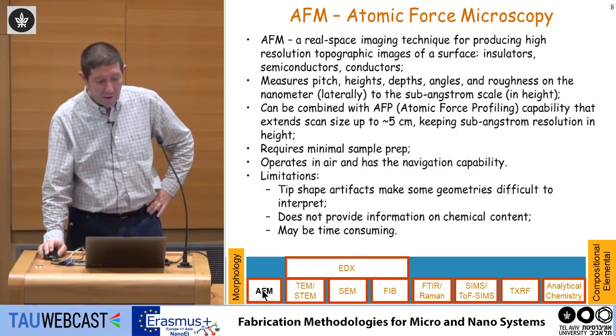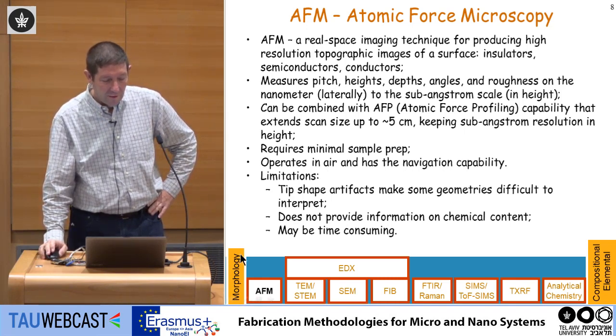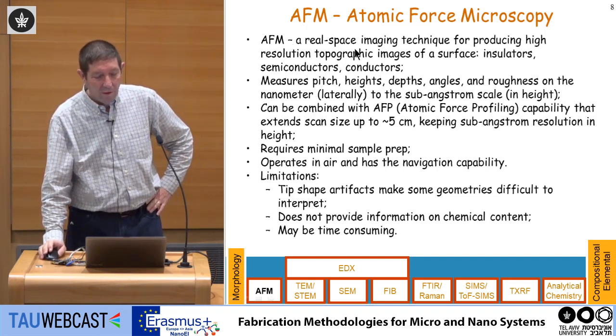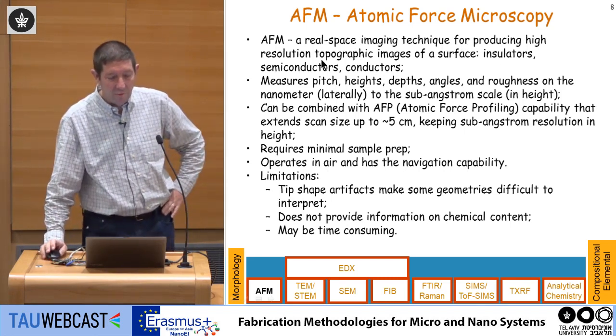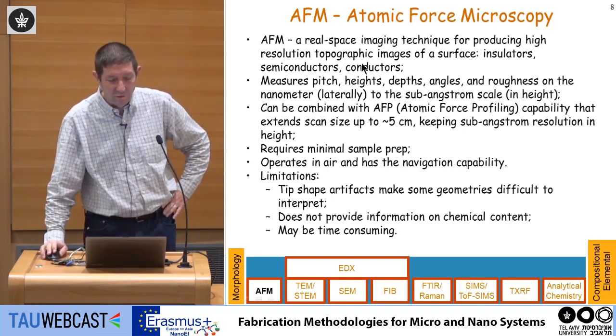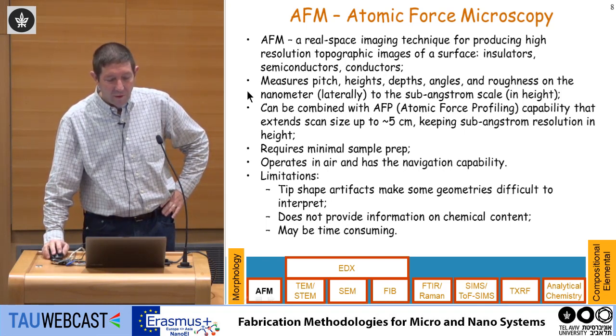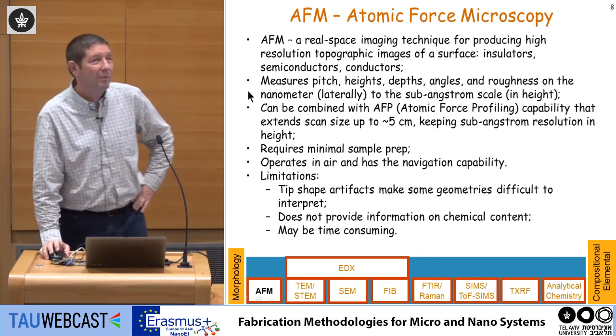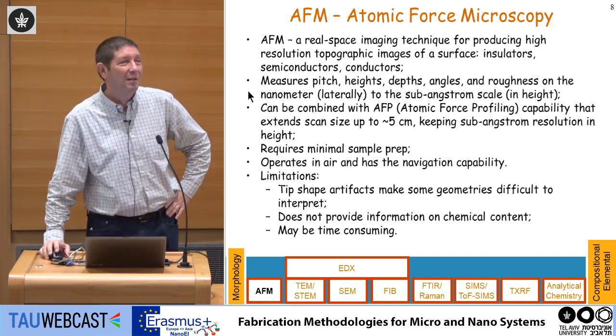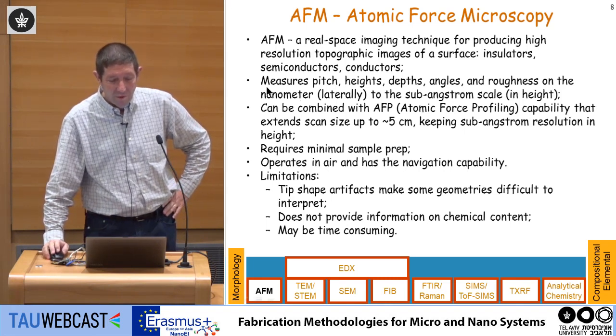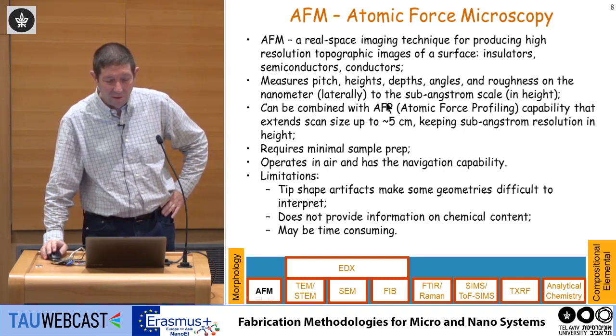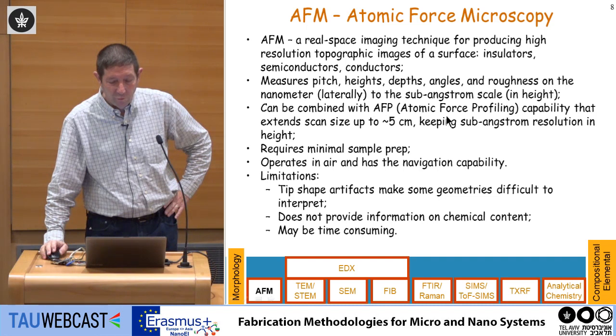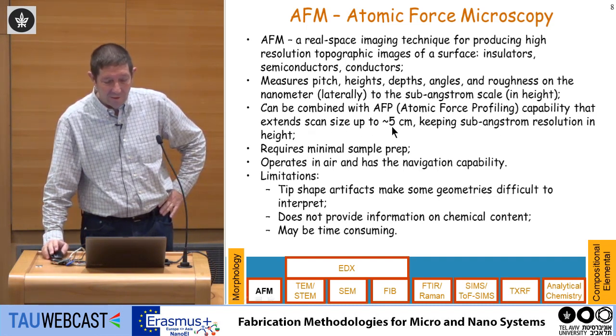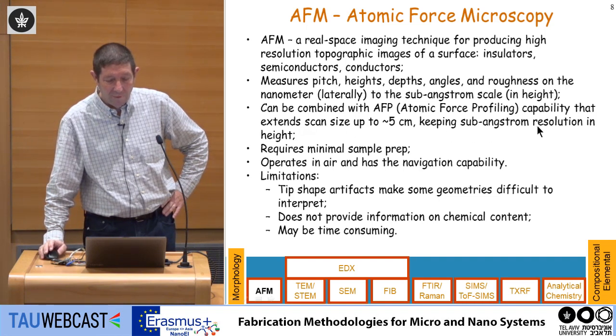This is the one on the leftmost on my list, and this is used to measure morphology. AFM, atomic force microscopy. It's a real space imaging technique for producing high-resolution topographic images of a surface, insulators, semiconductors, and conductors. It's a relatively new technique. When I was a student, it did not exist, but in the last 20 years, it became a dominant technology because you can measure pitch, height, depth, angles, and roughness of the surface in the nanometer scale. Can be combined with atomic force profiling, which extends scan size up to 5 centimeters, keeping sub-angstrom resolution in height.